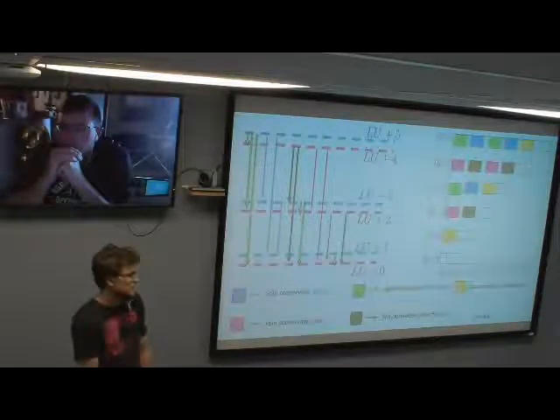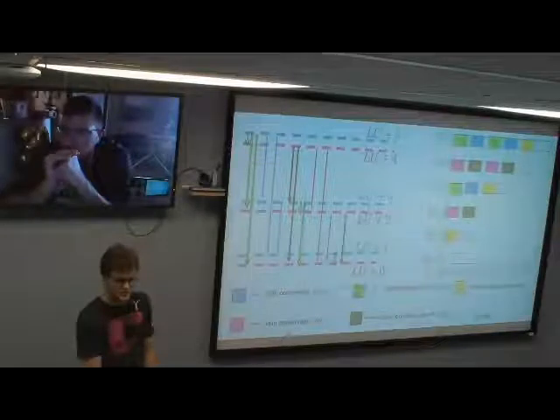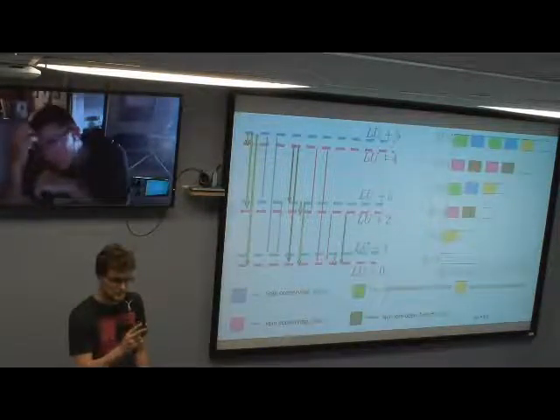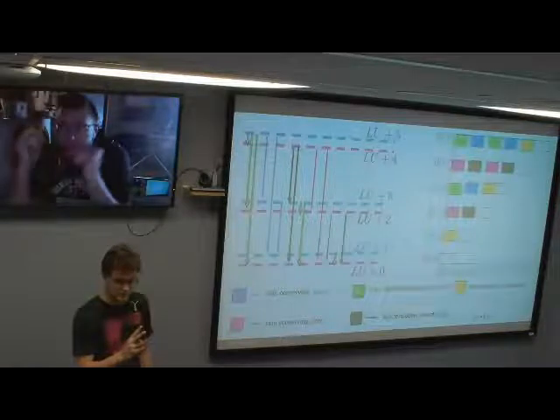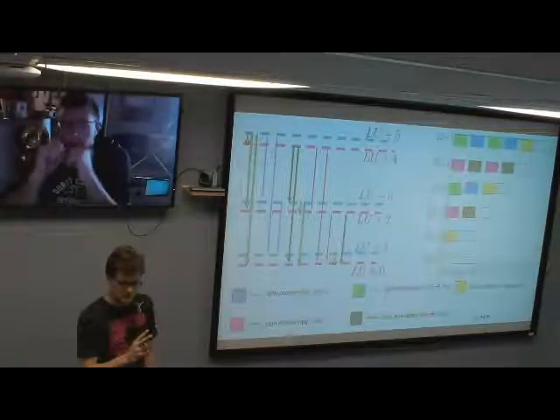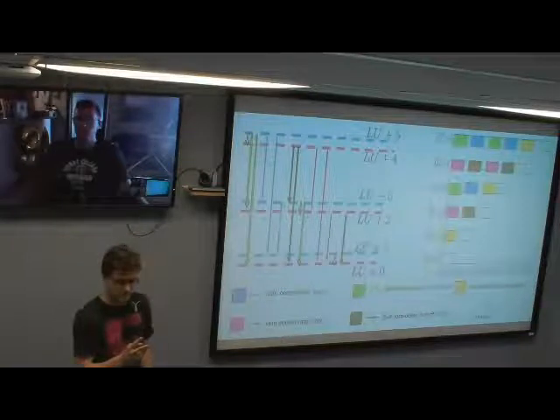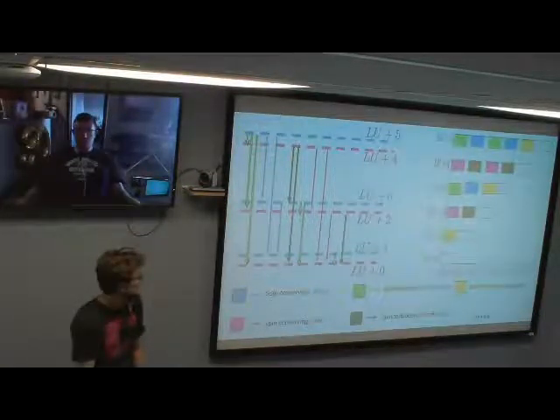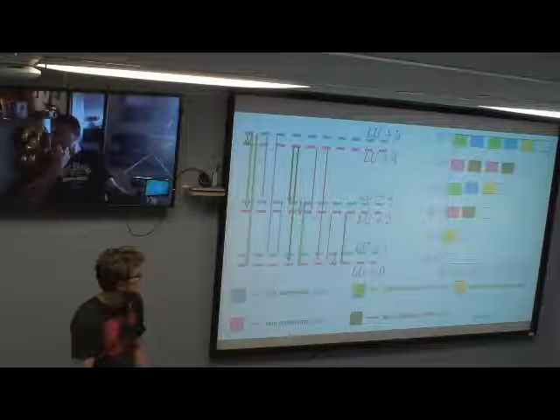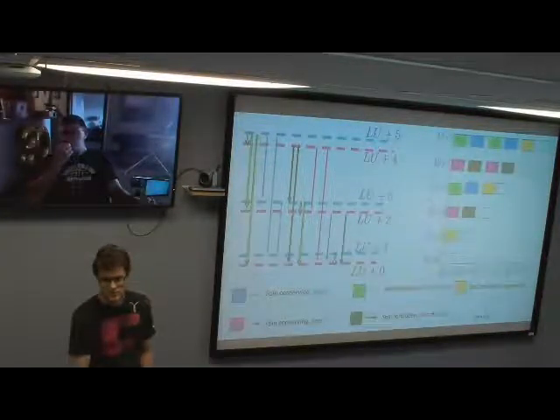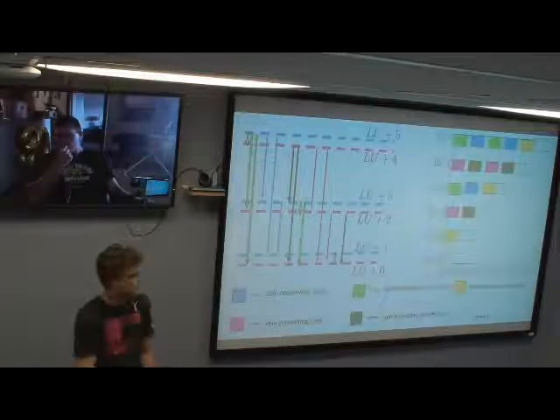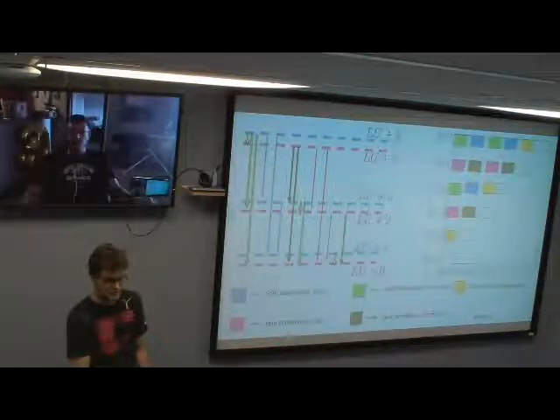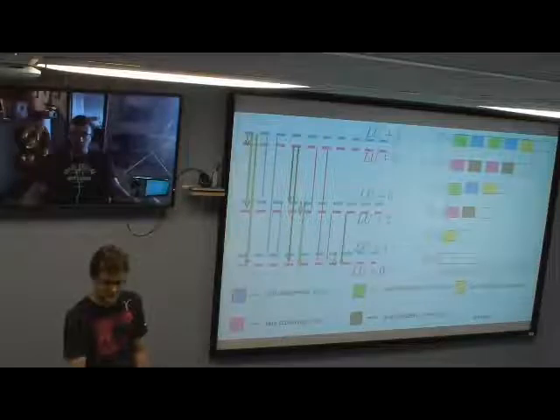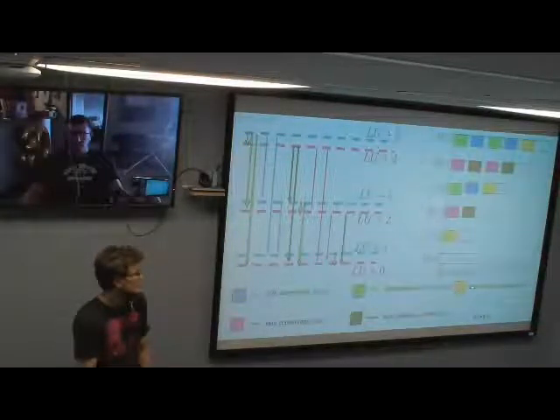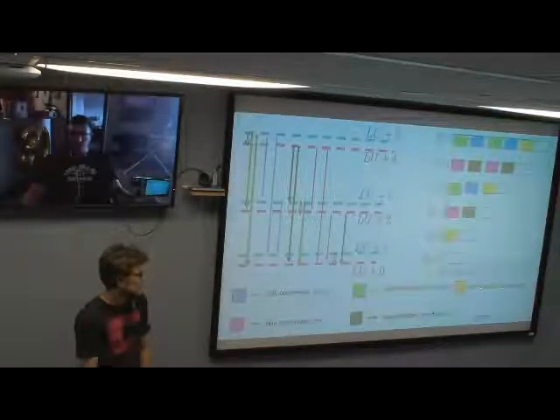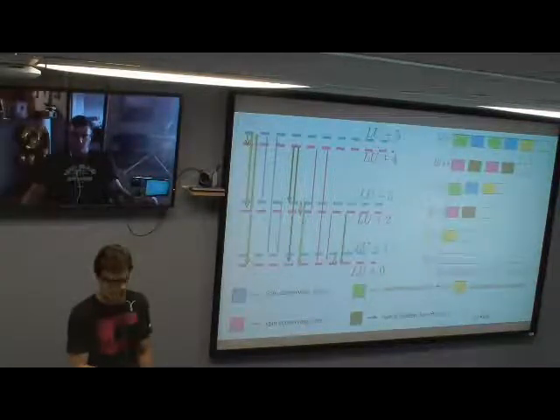I guess for our system, if you include spin orbit coupling, you always get two degenerate states near the band edge. So your LUMO and LUMO plus one are. This is without spin orbit. Yes, it is non-collinear spin, yet without spin orbit. So if you wanted that transition, you'd have to include spin orbit. Then it would just become a different color block, or we just name it differently. We would say spin orbit coupling transition or spin flip transition.